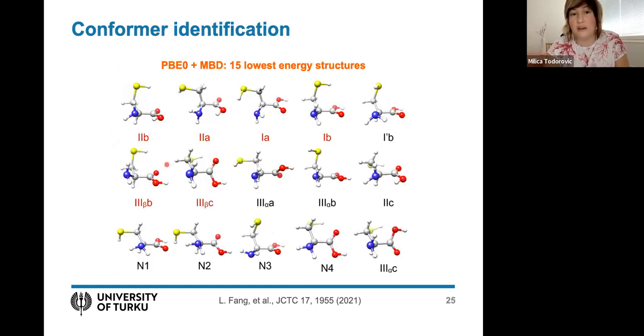So what I'm showing you here is that in five dimensions, we extracted lots of different local minima, and they are shown here. This top row are the lowest energy ones, and then the bottom row are the higher energy ones. These were extracted at reasonably high levels of theory, so sophisticated dispersion and a hybrid functional. Immediately we saw that these structures in red were the ones that were measured in experiments.